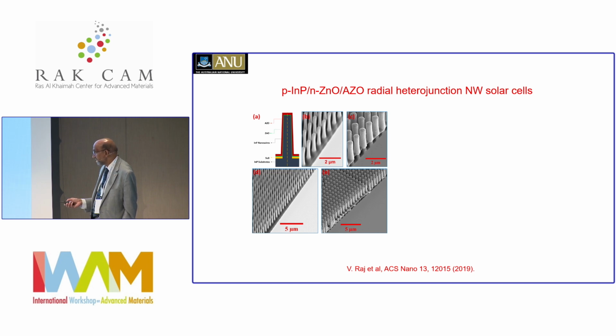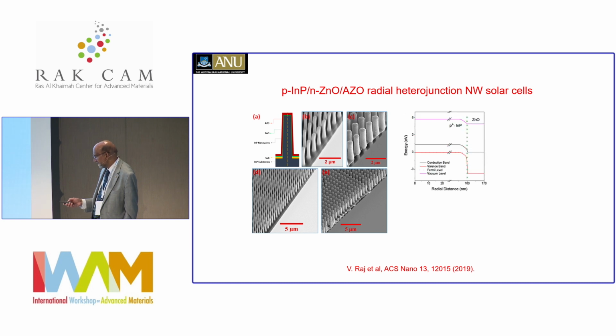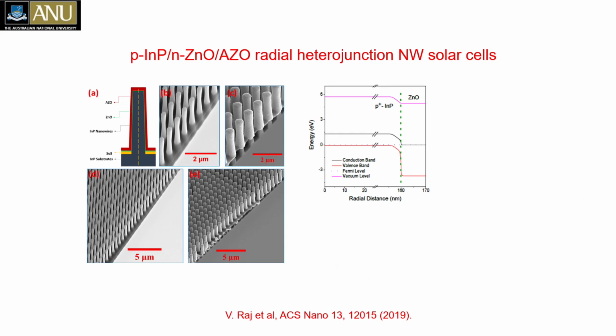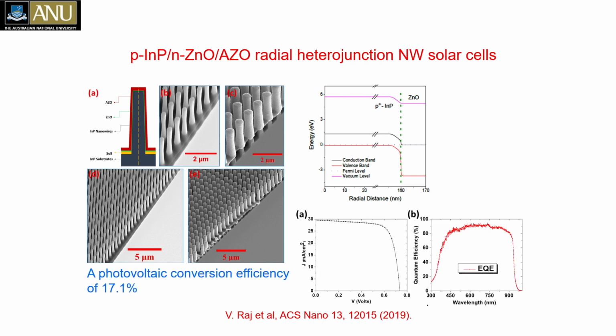And then, based on those simulations, we've fabricated these P-type indium phosphide nanostructures, nanowires. And then we coat them with N-type zinc oxide by using atomic layer deposition and an aluminum-doped zinc oxide so that you can make PN junctions. And they conformally coat these. And then we look at the performance of these particular solar cells. We're able to show that these nanowires have been showing about 17% efficient solar cells or so. This is the first attempt we made.